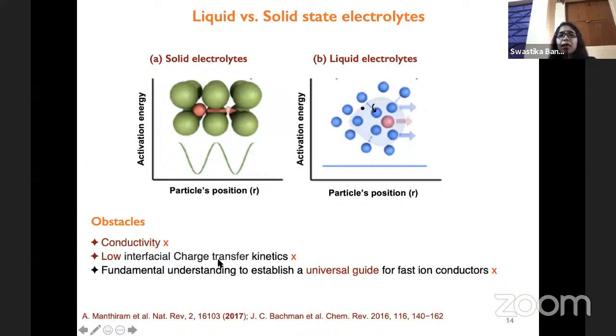So the main obstacle with the solid electrolyte is the conductivity, because it's very hard to find a low activation barrier with the solid. And it's very hard to get low interfacial charge transfer kinetics between two solids when you combine the solid electrolyte with the electrodes. And fundamentally, we do not have any guiding principle to design a solid electrolyte. So these are the main three obstacles to getting a new material which will be a potential solid electrolyte.